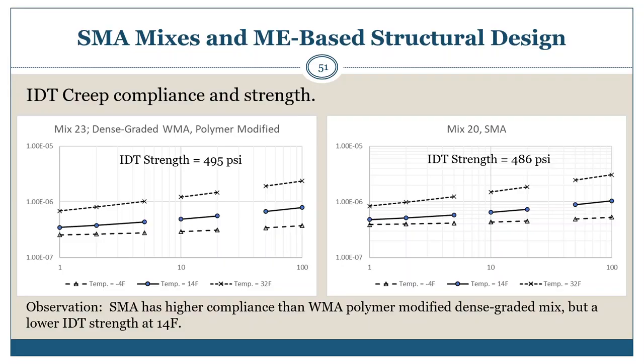Indirect tensile strengths of SMA mixes are generally lower than for conventional dense graded mixes because of the higher asphalt contents. The creep compliance values, however, generally control the resistance to thermal fracture and are more important than the indirect tensile strength.